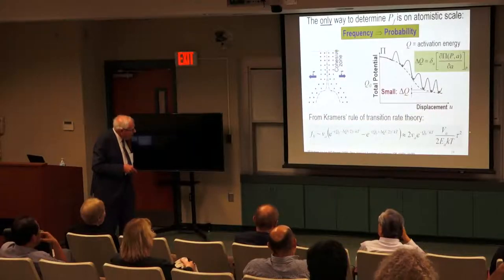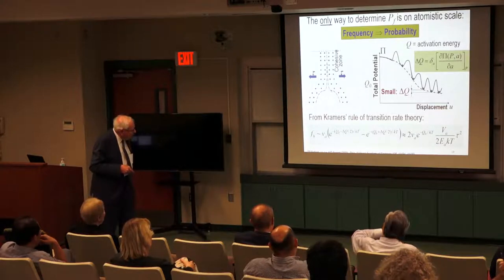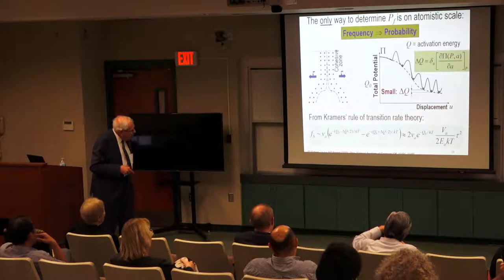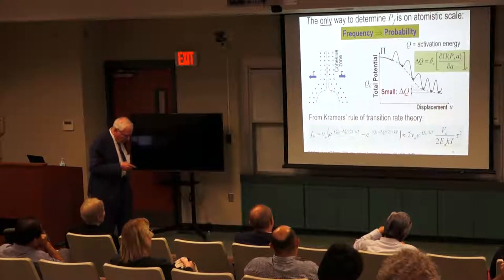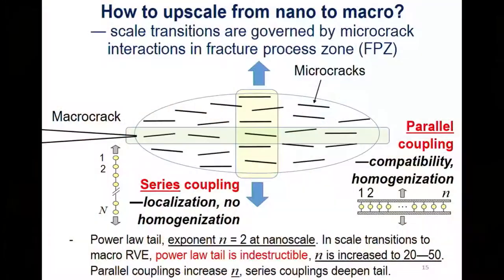The argument is this. This is the stress, the applied remote stress, squared. And this is a thermal term which is multiplicative. The main thing is this: it's a power law. So the tail distribution is a power law. All right. So now this is on the atomistic scale. Now, the Weibull distribution has a power law tail.